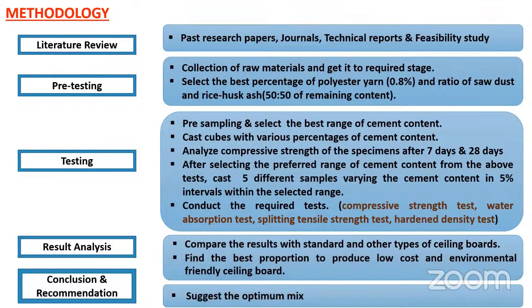Testing: pre-sampling and select the best range of cement content, cast cubes with various percentages of cement content, and analyze the compressive strength of specimens after 7 and 28 days.